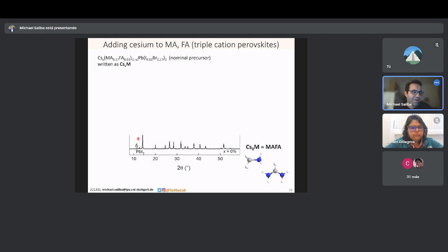And I thought it was very curious. So although these materials are leading, they are still full of impurities. If you are from the silicon community or the 3-5s, this is a very strange thing to observe. So one idea was to say, well, since they are working very well, can we tweak them a little bit by adding small bits of cesium, for example, in order to get rid of the delta phase, because it's an example of the polymorphism that I've alluded to earlier. So by adding systematically larger amounts of cesium, all of a sudden the delta phase disappears, and even the lead iodide excess is eaten up as well.